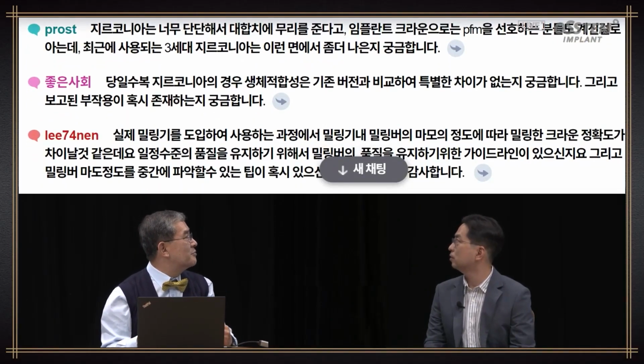Zirconia is known to cause harm to the antagonist because it's so strong, and some people prefer PFM for implant crown. Is this improved in 3rd generation zirconia? Causing wear on antagonist because it's too hard. I think it's because of premature contact. Some patients are more sensitive, and therefore, in the case of zirconia restoration, you need to remove a premature contact for sure to reduce patient discomfort. I think that is most important.